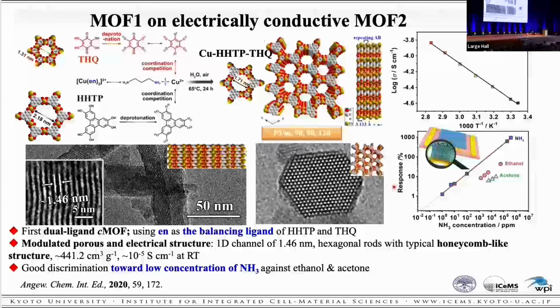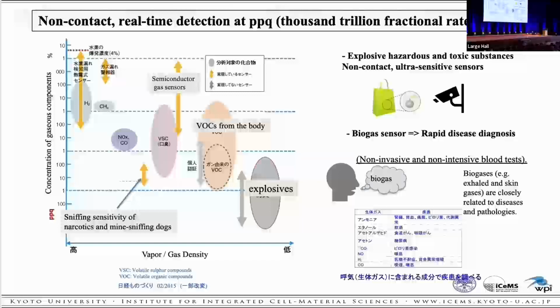The dynamic sensing curves of this material over a broad range of ammonia concentrations, 1 ppm to saturated vapor, showed good response and recovery properties at room temperature. Notably, the sensor showed good discrimination of ammonia in the low concentration range, 1 to 100 ppm. So, non-contact real-time detecting at the PPQ level, 1000 trillion fractional rate level. That is very important.